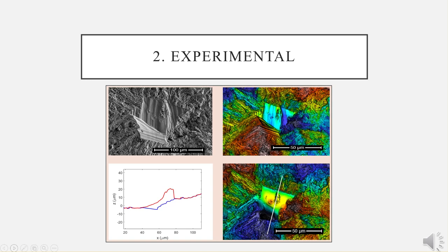Thus, we can determine whether the defect is blunt or crack-like, and quantify the notch radius. In this particular example, we find a surprising result. Instead of being a blunt or a crack-like defect, we see a combination of both situations.